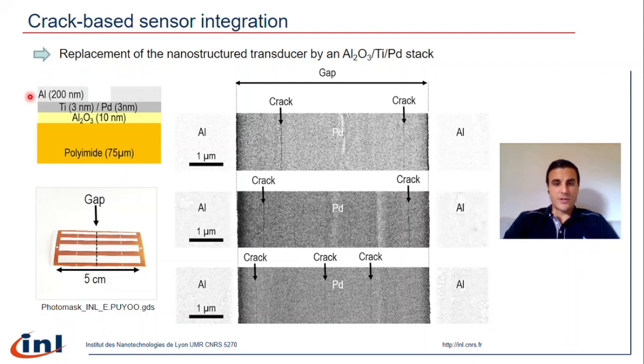In order to generate the cracks, we have placed the flexible sensor in a buckling configuration between two translation stages. As you can see here on the right, on these top view SEM images, we could easily generate 2 or 3 parallel cracks within the gap between the two aluminum top contacts at a strain level of around 1%.